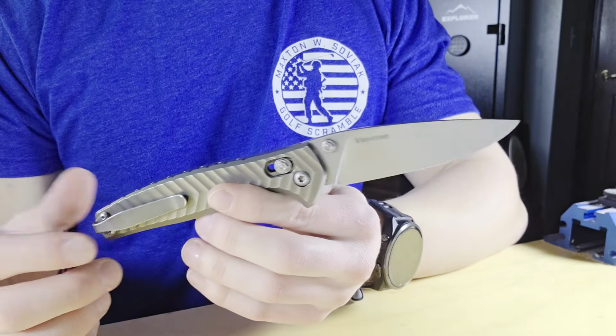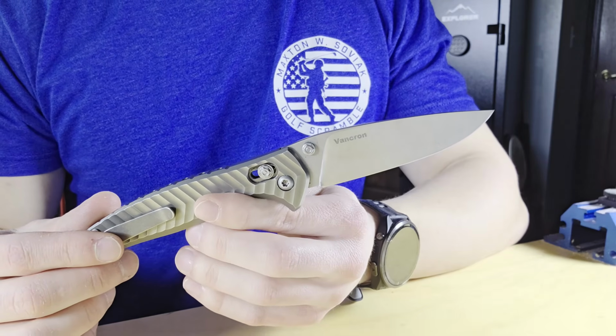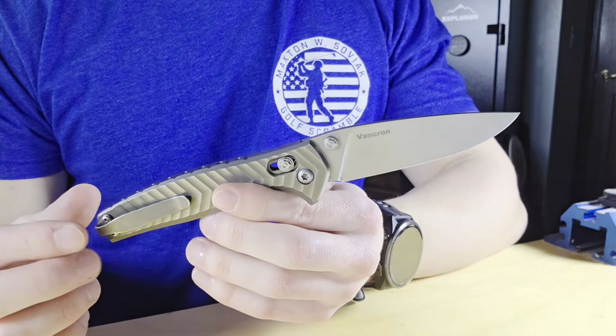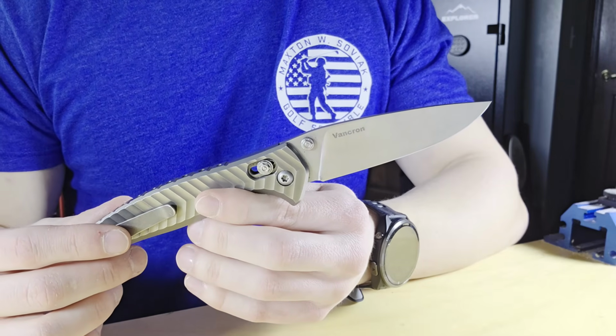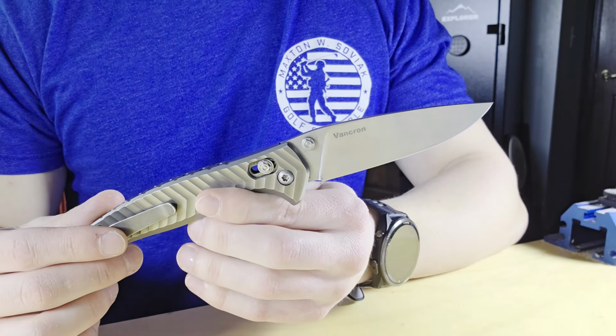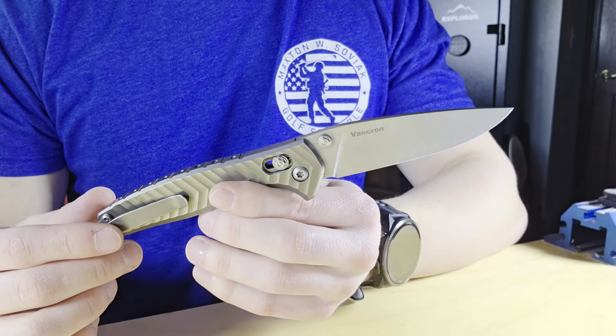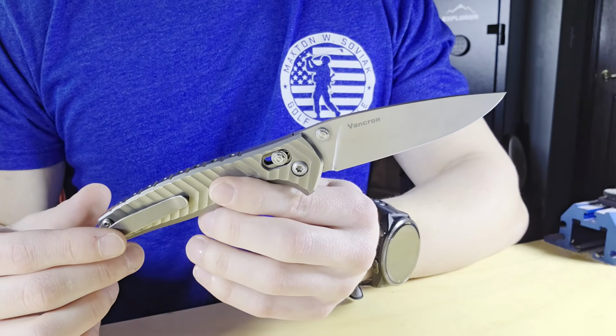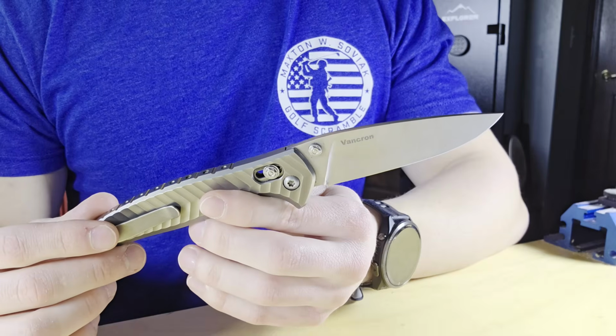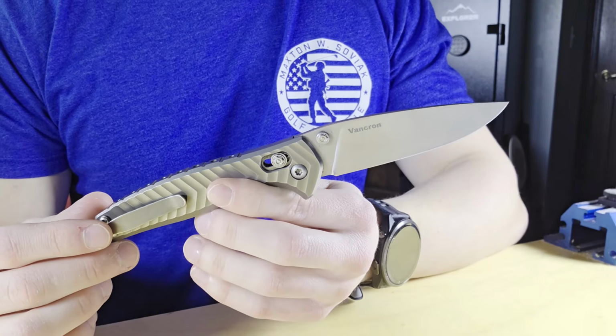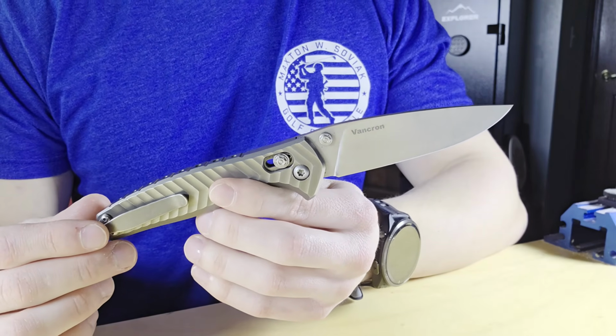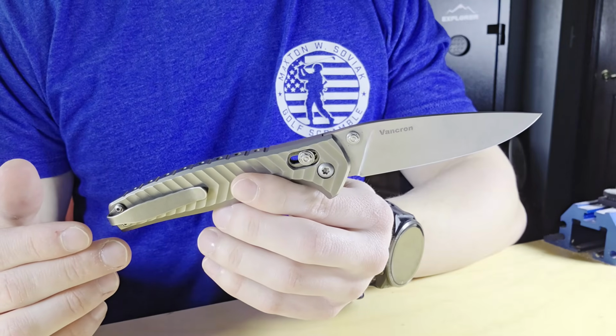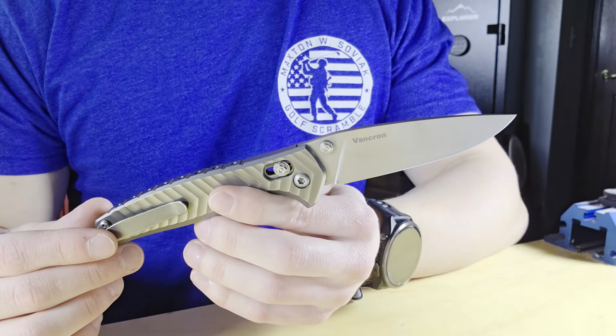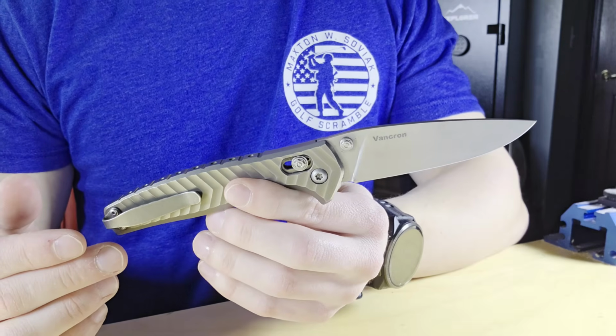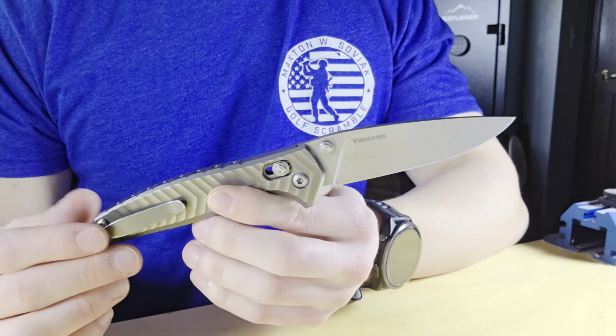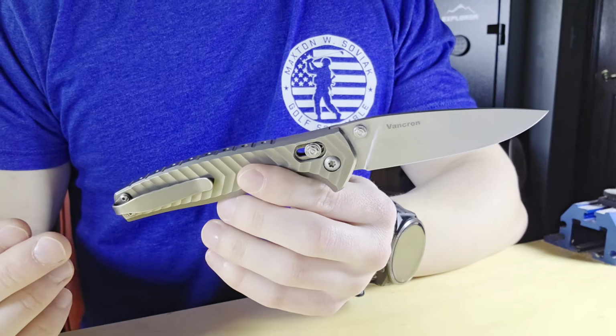Through trial and error, though, I've discovered that there's really no clear number to stop at, since the BESS scores are an average across that 1-inch section that I cut in, and the paper test can stop as soon as there's one small spot that's taken enough deformation to catch in that spot. Throughout a dozen or so tests with plotting BESS scores, the range that they stop at ranges from 315 BESS all the way up to 463. So this ended in that range, but you can see how using those numbers on when to end the test isn't really a perfect science, so I can't really do that.